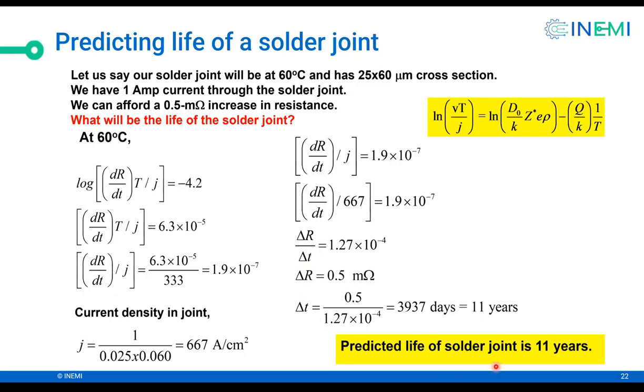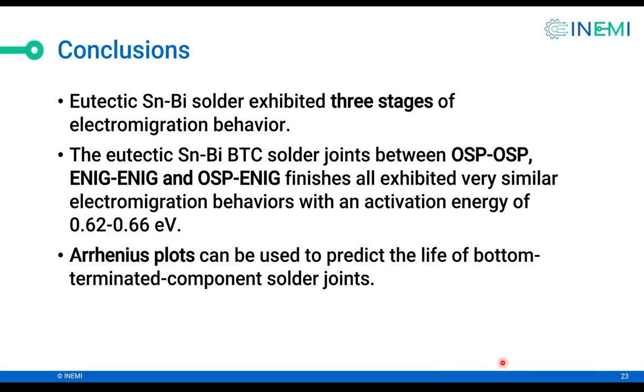So that's straightforward. So the conclusion of the first half of today's presentation is that tin bismuth eutectic solder exhibits three stages of electromigration behavior. And the eutectic solder, tin bismuth, whether it's between OSP metallization or ENIG or ENIG OSP, exhibits very similar electromigration behavior with an activation energy of 0.6 to 0.66. And as I explained, the Arrhenius plot can be used to predict the life of the solder joints if we know the temperature and the current density. So this is the first half.